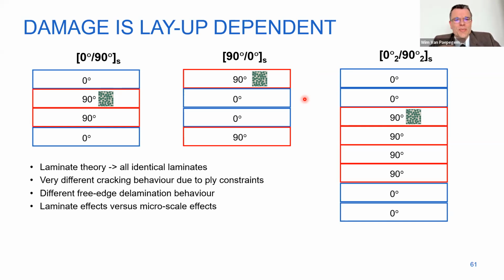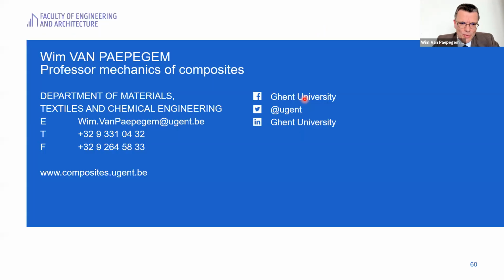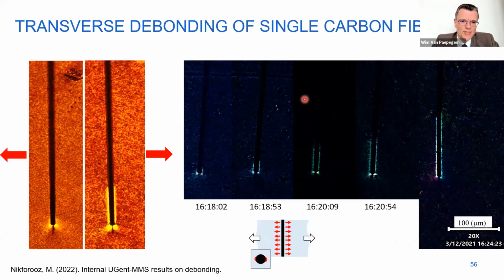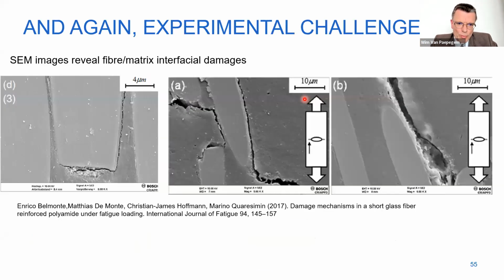Yeah, it's again a bit related to the interface. So I will go back to this slide here. This is now a single fiber in a polymer, and we can have well-controlled testing conditions. But for example, if you want to follow how these damage mechanisms evolve over time, this is post-mortem after failure. There are some experiments in synchrotron, where people go to a synchrotron here in Europe. You have the one in Grenoble, in Zurich. You have in Japan. You also have a few. I guess certainly you have in the US as well.